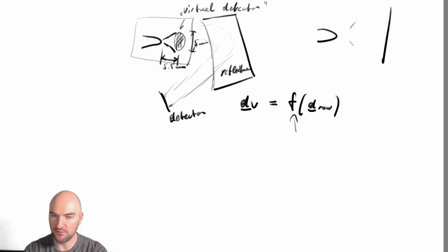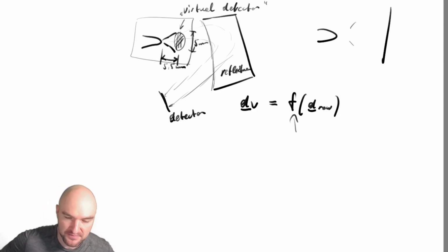But if you have a LEAP 4000 or 3000 SI, you can change the flight path length. Yeah, you can run it at 90 millimeters, you can run it at 110 millimeters. You can actually change that length. I don't think the newer ones can do that anymore. It wasn't that useful in the end anyway.